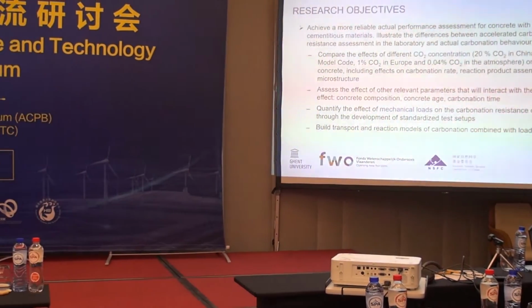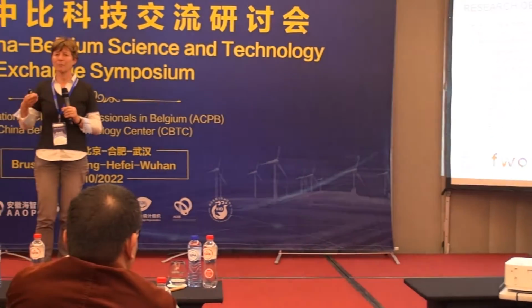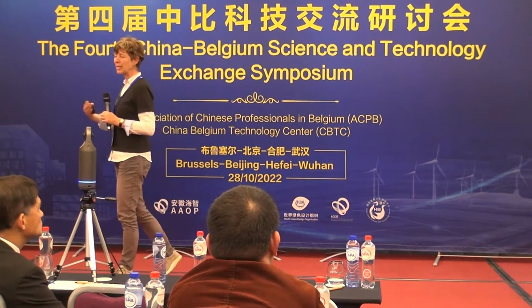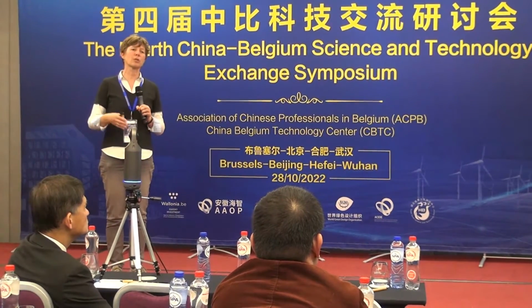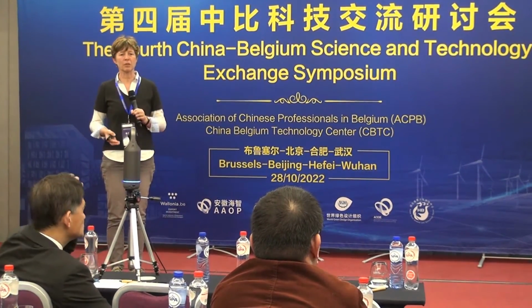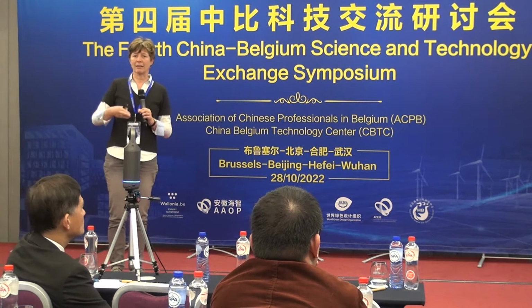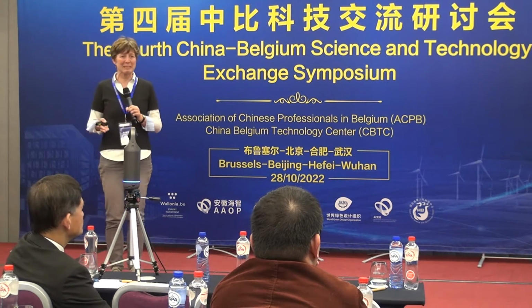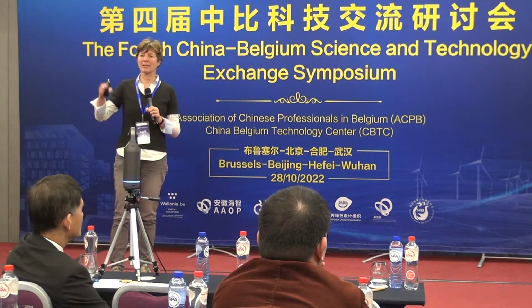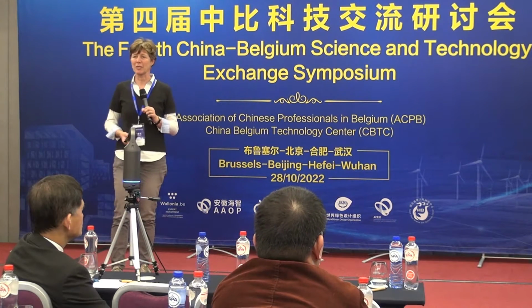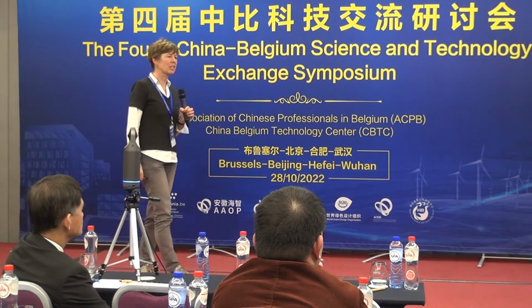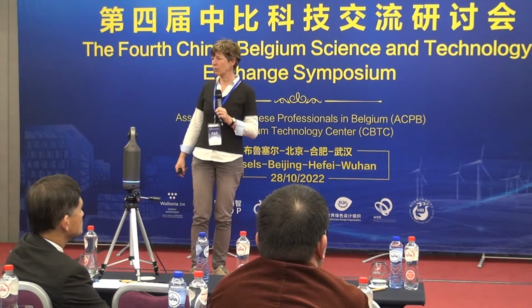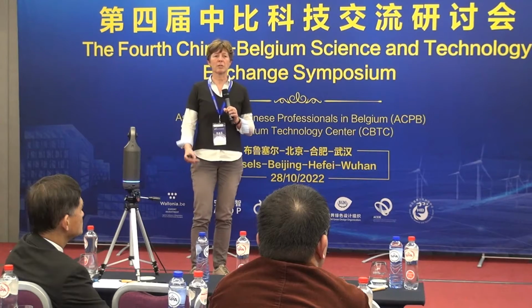However, if you have pozzolanic materials that react with this Portlandite to form new binders, well, this is positive, of course. That's why we can use them as alternative binders. But on the other hand, it has the downside that you lower the buffering capacity and that carbonation of the concrete can go faster. And I think since this is a session about construction, maybe you know that when the concrete is carbonating, it's not bad for the concrete itself, but when the carbonated zone is reaching the steel reinforcement, it can start to corrode. And that is then one of the most important problems of concrete degradation.